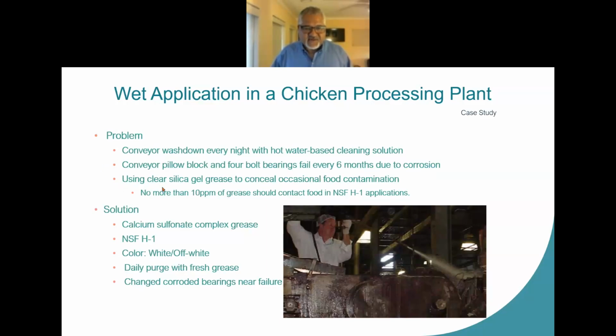They're using a clear silica gel grease to conceal occasional food contamination. Boy, that raised a red flag to me, but there's not much I can do about it. They probably know it. That's why they're concealing food contamination with the grease, because according to NSF, you cannot have more than 10 ppm of grease contacting your food. And so they're definitely contacting food with the clear grease quite a bit, just so they can maintain the production rate and still use the grease. I mean, that was just their best solution at the time.